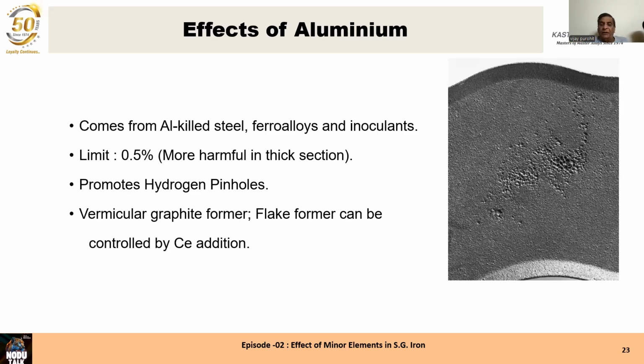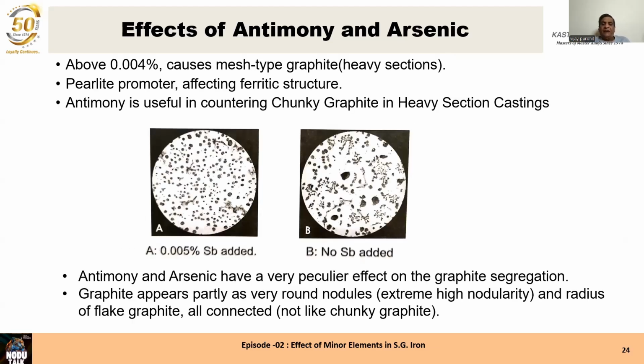Hydrogen pinholes are promoted by aluminum. And vermicular graphite is formed. Flake formation can be controlled by adding cerium. So when aluminum is present, you have to make sure that you're using cerium to take care of aluminum. In the first place, please do not use aluminum containing steel scraps, especially high silicon steel scrap, which is having high levels of aluminum. Effects of antimony and arsenic.